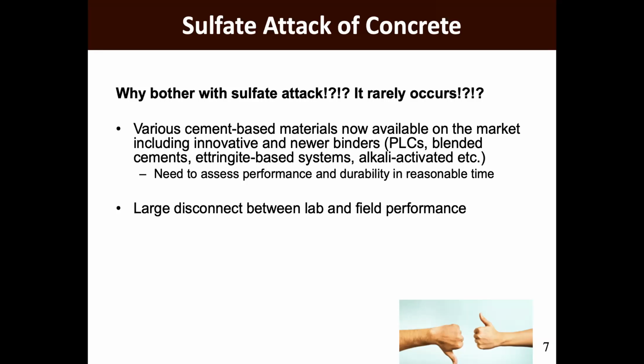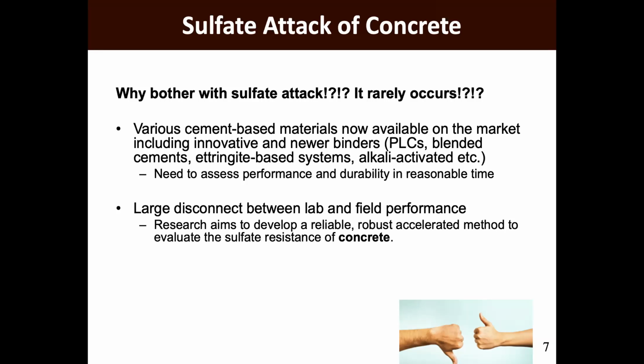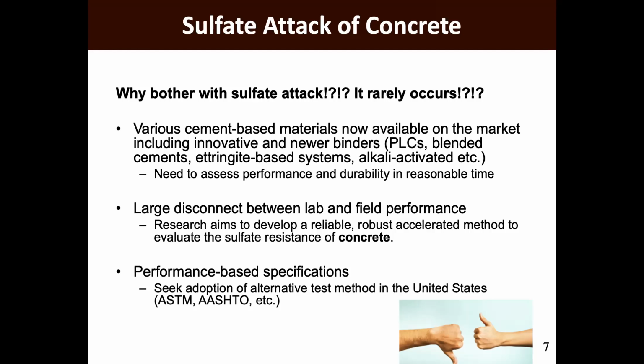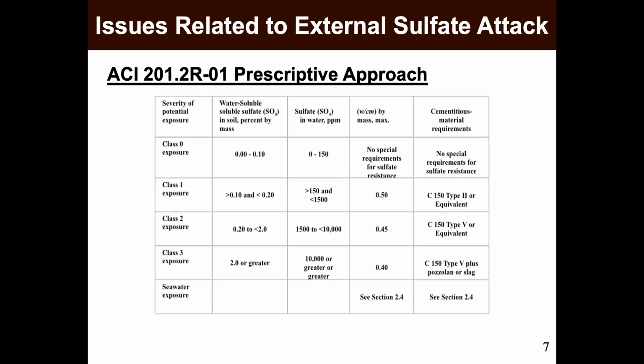Secondly, 1012 has been given a bad reputation for having a large disconnect between lab and field performance. What we're aiming at is developing a method that doesn't just accelerate, but also gives the ability to test concrete, whereas the 1012 method uses a mortar. So it's still quite a disconnect from what we actually do in the field, where we normally work with concrete. And performance-based specifications are becoming pretty popular nowadays, so ideally we want to find adoption into ASTM specifications.